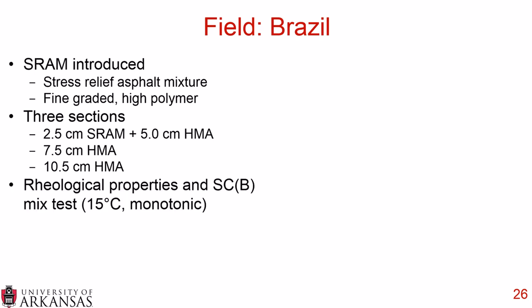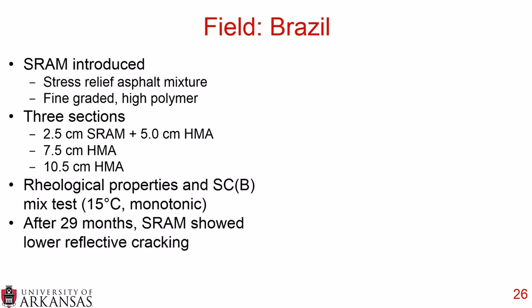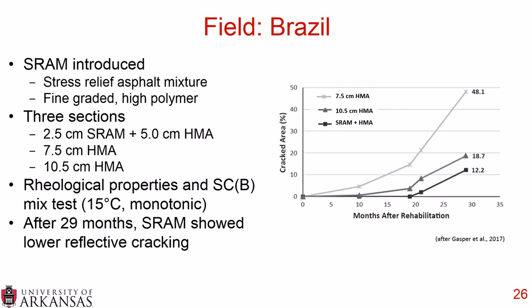Now in the lab, they ran a whole bunch of rheological property tests, which is very interesting, and they ran the SCB, the semicircular bend test, at 15 degrees Celsius in a monotonic fashion. So they did a whole bunch of lab tests, but they also looked at this field, and they found that after 29 months, the SRAM showed lower reflective cracking. And they actually have a very nice graph here that demonstrated that.